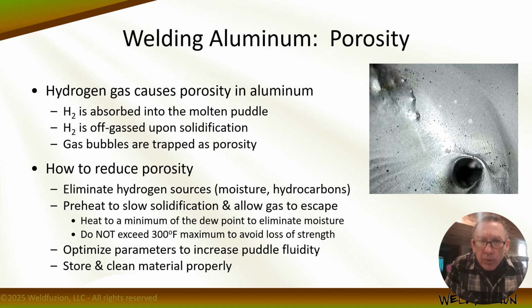Yeah, we could preheat. We could have added argon or helium to our shielding gas to slow the cooling rate. We could have lowered the frequency down to 60 hertz. I mean, we would have missed the whole point of using inverter technology. So instead, what we did is we told the operator to take a deep breath and allow that weld pool to slightly flatten out prior to adding any filler metal and progressing with their weld. And the result, that slight hesitation made all the difference. It slowed the cooling rate enough that the porosity was completely gone and we did not have to change the parameters at all. We just had to adjust the technique to deal with a new arc characteristic.